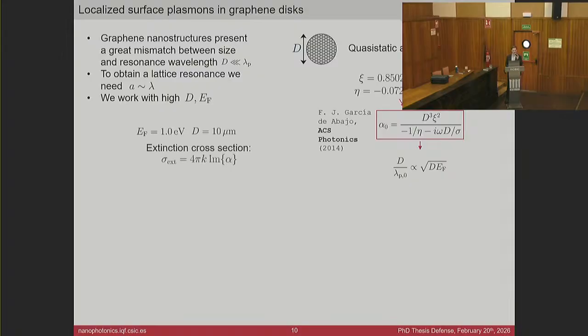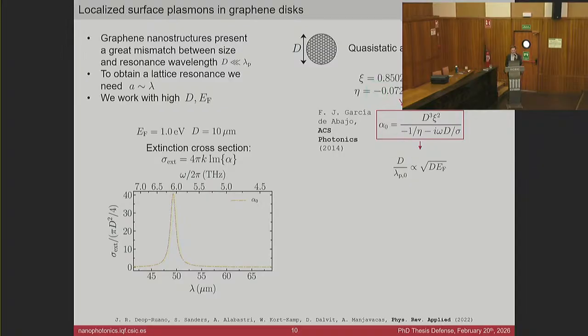Let's explore a case. I'm going to analyze the optical response of the nanostructures by means of the extinction cross-section, that more or less tells us how much light is removed from the incident excitation. And we plot it for this polarizability, obtaining this result. We can see a resonance, a particle plasmon. But now, if we compare the results that we obtain for this quasi-static polarizability with finite element method simulations, we see that there is a big mismatch. And this is something that actually we could expect, because by choosing these parameters, by going to high diameters and Fermi energies, now we have a diameter that is smaller, but at least comparable to the resonance wavelength, and we are moving beyond the regime of application of the quasi-static approximation.